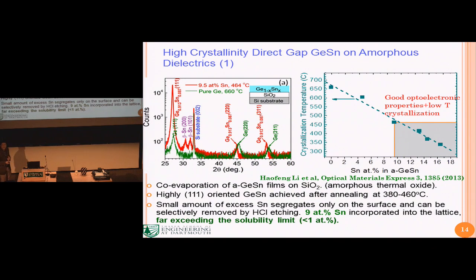I like that. Okay, so here are some results from our research. Initially, my student has tried to deposit this amorphous germanium tin on silicon dioxide dielectric layers, which are used to isolate electronic devices in photonic circuits. We do this co-evaporation, and what we found is that the crystallization temperature keeps decreasing with the increase of tin composition. This is something we actually expected. Something we didn't expect is that these transition temperatures are very well defined. It looks as if it's a phase transformation. Once you reach that transition temperature, the crystallization can happen in just 60 seconds or so. And if you're below that temperature, it takes forever.